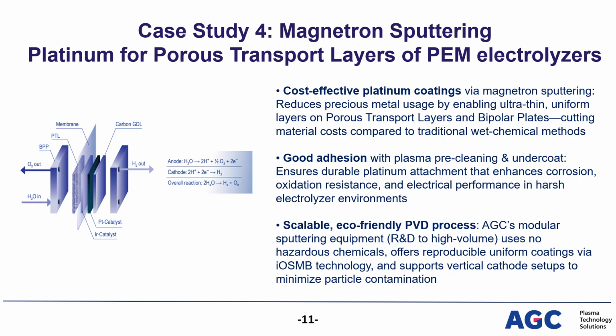Considering the acidic environment at the anode side of the PEM electrolyzer, the titanium needs to be protected with a thin anti-corrosion layer, and platinum is widely used. AGC implemented a plasma etching process for the PTL, followed by a sputtered undercoat and a platinum layer applied by HiPIMS power supply. The use of HiPIMS power supplies for the deposition of undercoat and platinum layer allows for the deposition of dense layers with superior adhesion to the PTL.